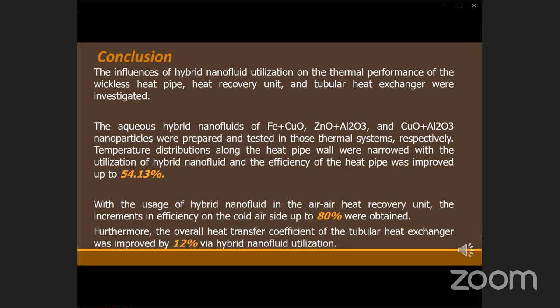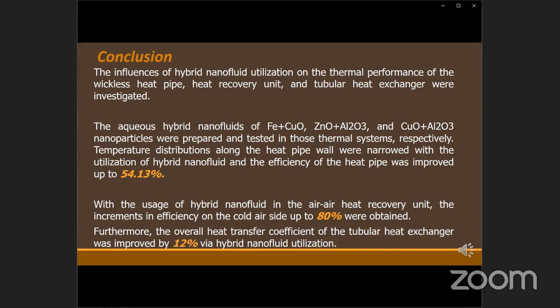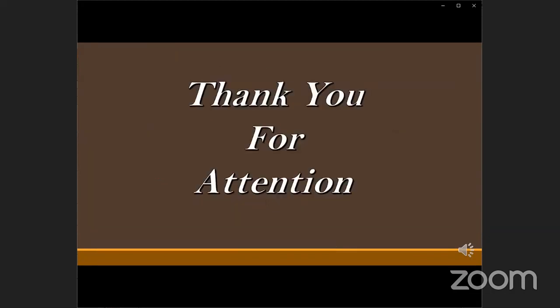Temperature distributions along the heat pipe wall can be narrowed with the utilization of hybrid nanofluids, and the efficiency of the heat pipe can be improved. With the usage of hybrid nanofluid in the air-to-air heat recovery units, the increments in efficiency on the cold air side up to 80% were obtained. Furthermore, the overall heat transfer coefficient of the tubular heat exchanger was improved by 12% via hybrid nanofluid utilization. Thank you for attention.